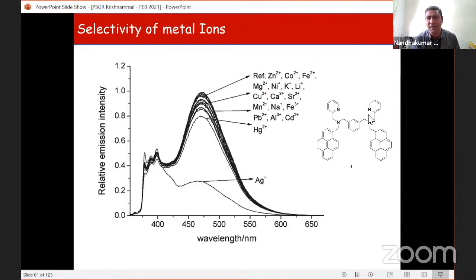So when you take the first one, you can see we have tested several metal ions: magnesium, zinc, cobalt, iron, nickel, potassium, lithium, etc. But for this peak, for silver alone, quenching takes place. So these two are monomer peaks. This is one, two monomeric peaks for pyrene, and this is the excimer.